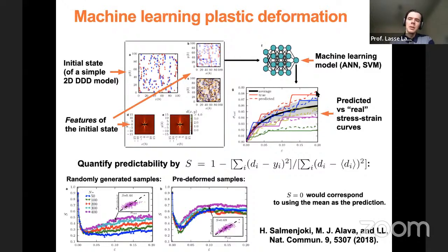Here are some examples shown with dashed lines. So the predictions are these dashed lines. The actual true ones that you simulate using the model are the solid lines. And then there is some average for this data set, with some standard deviation. So you see that while the predictions certainly are not perfect, so they are not able to resolve these fine details of the stress strain curves, these individual steps or individual strain bursts, if you like, they still follow the general trend of each of these curves. So definitely the machines have learned something. The predictions are not perfect, but they are decent at least.